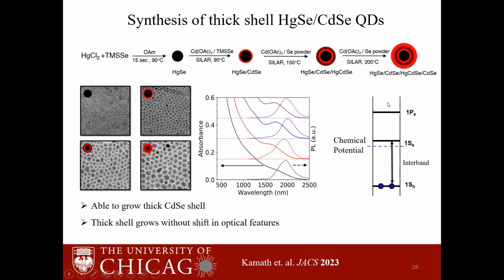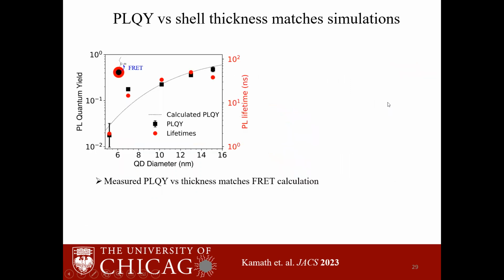After the synthesis, we measured the quantum yield as a function of shell thickness. The y-axis is the quantum yield for mercury selenide, cadmium selenide quantum dots with different diameters. The black points are absolute quantum yield measured in an integrating sphere. The red are lifetimes measured in collaboration with Rich Schaller at Argonne. And the black dotted line is the ligand FRET calculation between our core quantum dot and the ligands. We can clearly see that all of these three trends match quite well.